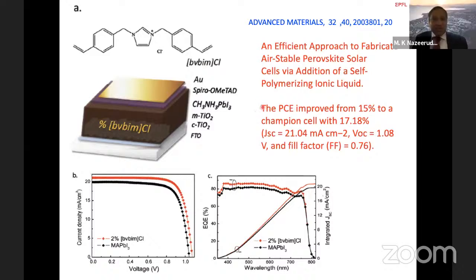Okay, thank you. So I have another ionic liquid which I have to show here. This is the ionic liquid with double bonds on both sides. This is a vinyl ionic liquid. When we use this ionic liquid with the standard perovskite, methylammonium lead iodide, which is extremely unstable, you can make these perovskite solar cells outside. As a reference sample, the efficiency is only 15%. That corresponds to this black IV characteristic.